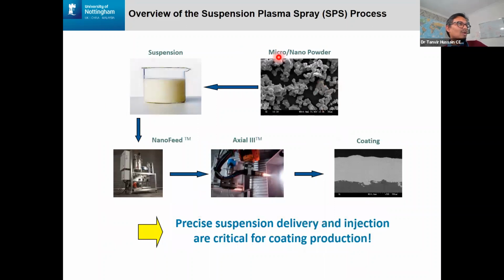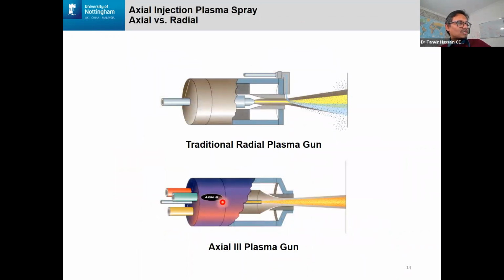And this is how the cycle looks like. We start with submicron or nanoparticles. We turn them into a suspension, and there are commercial companies who will make this suspension; small quantities of suspension we can make ourselves. It goes through a suspension feeder and plasma processing, and it results in a coating. I will be showing you quite a lot of scanning electron microscope images of coating. So that's a bit of the coating on a substrate, just to show that it's a relatively dense coating, well adhered to the substrate. So the concept here is with the axial one, we're injecting the suspension axially.